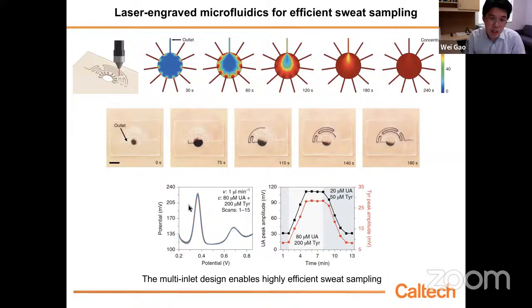And we did a microfluidic test. If you look at how we are detecting uric acid, for example, if we keep doing repetitive detection for 15 cycles over 15 minutes, the sensor remains very stable in performance. If you change the target concentration from 20 to 80, it only takes around 2 minutes to reach the new stable reading. That means that even though there is a delay, it's minimal, a few minutes, and we think it's pretty good already for wearable sensing purposes.